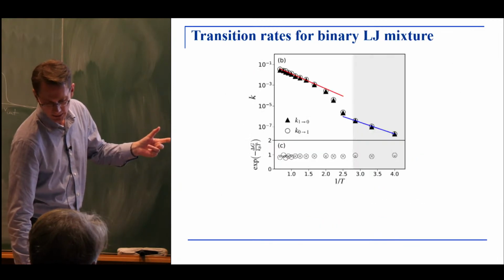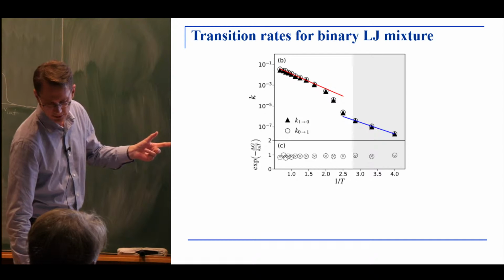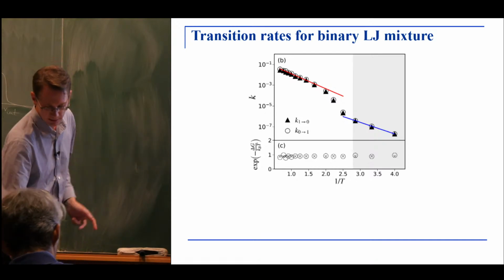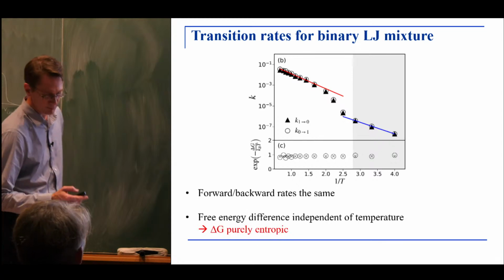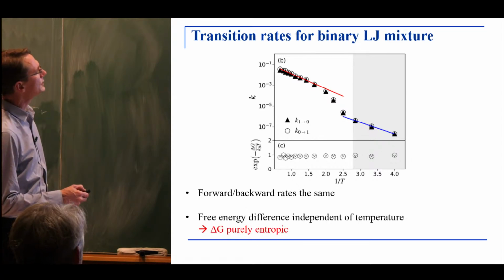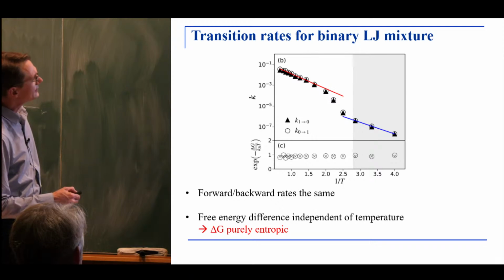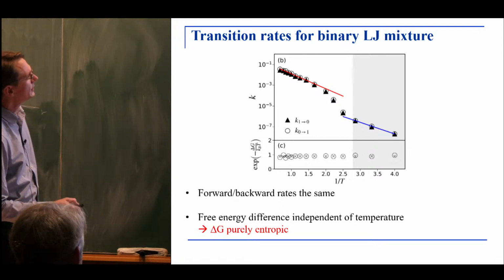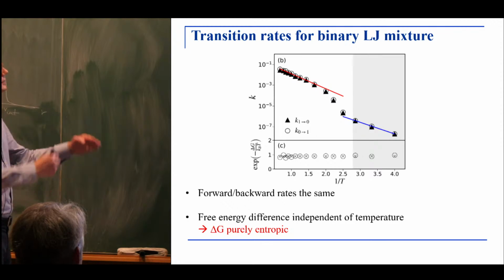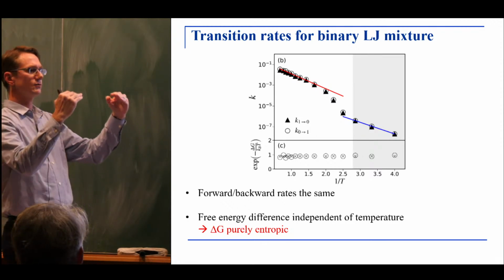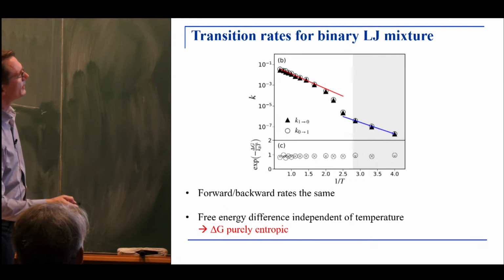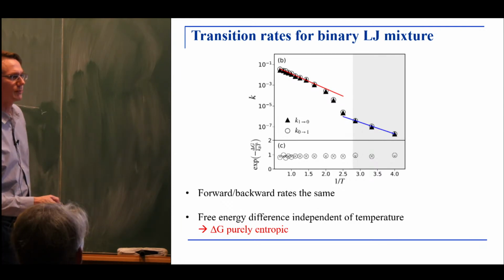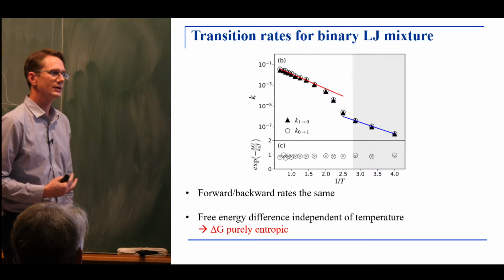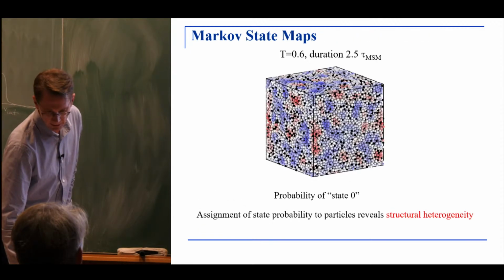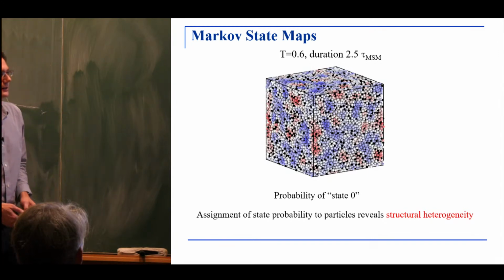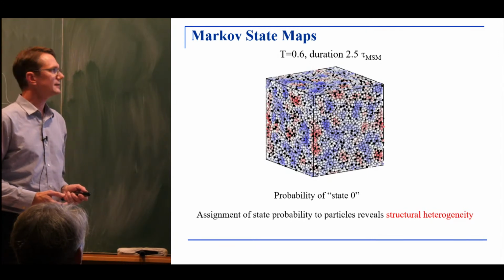Okay, so maybe I skipped this slide. This is just showing you the transition rates. Forward, backward rates are the same. An interesting feature is actually this bottom panel here, which is the ratio of the eigenvectors. And what you can see here is that this ratio is independent of temperature. You can interpret this as the free energy difference between the two states in the Markov model. And if you find this to be temperature independent, then this suggests that the free energy difference is mostly entropic. So that's an interesting observation that one can make in this model here. All right, now let me show you a movie, or first a picture of this model here.